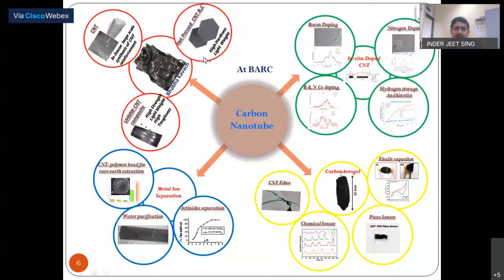On the left side you can see in ceramic matrix, we can add carbon nanotube in ceramic like boron carbide to improve its toughness and its fracture strength. Then in polymer matrix composite like ultra high molecular weight polyethylene to improve its stiffness. All these two materials have been used in the Bhabha Kavach, which is a lightweight bulletproof jacket.